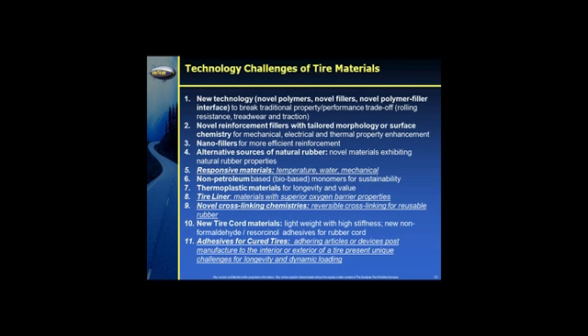Most tires use these days about a 0.5 millimeter to 0.75 of a millimeter of a butyl-based polymer to retain the air in a tire, keep it inflated, stop the air diffusing out through the rubber. Now, there are plenty of materials out there with better air barrier properties than butyl that could be used at lower thicknesses for weight reduction. However, there are a lot of significant challenges remaining in terms of the flexing tolerance of those polymers over millions of cycles and at low temperatures, maybe as low as minus 40 degrees centigrade, and with sufficient extensibility for manufacturing and service.